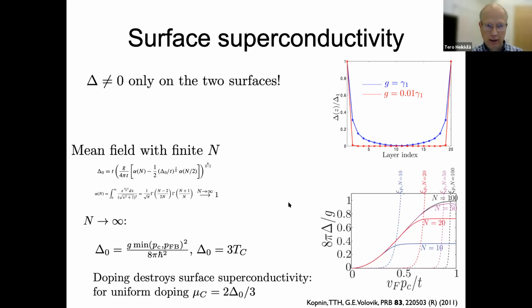The exact details will depend on the size of the coupling that you include, but the bottom line is that you get surface superconductivity. The delta becomes finite at the surface for a coupling that is not too strong, and then there is some decay that depends on the exact size of the coupling. You can also study how this delta depends on finite n. There's a pseudo-analytic formula for this delta, but for very large n you get the limit where delta is linearly proportional to the coupling strength. And from this delta you get a critical temperature by putting a factor of 3.